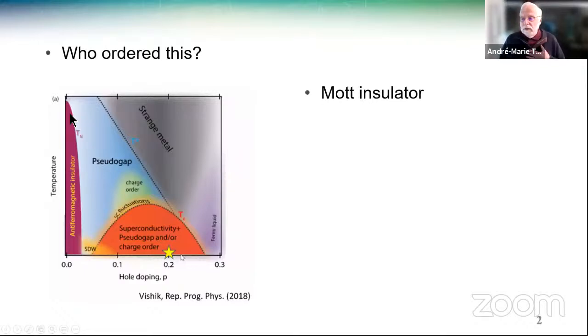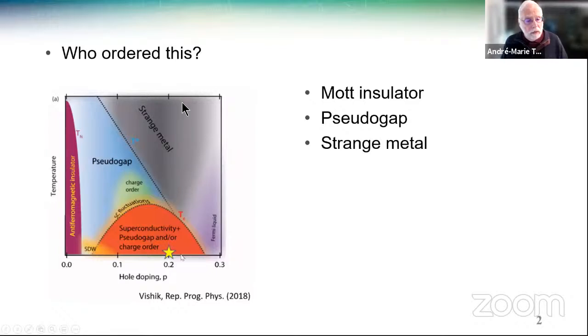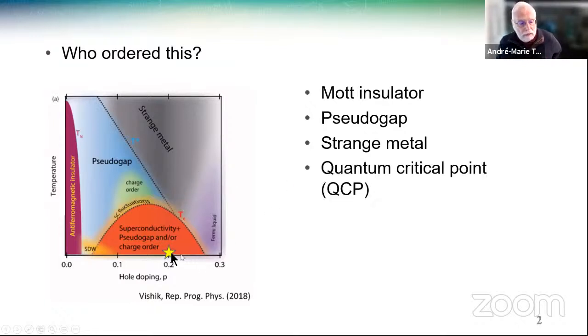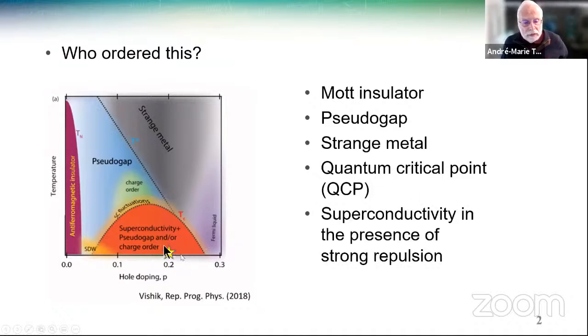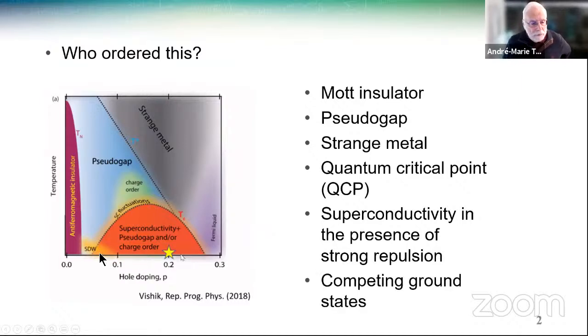In fact, you cannot use standard methods of solid state physics to understand it. For example, we know what an antiferromagnetic insulator is, but if you go above the Néel temperature, you have an insulator. Now, when you dope, so this is temperature, this is doping, you get this phase that is called a pseudogap. And here we go to a phase that has a linear resistivity, linear in temperature, that's called strange metal, and something that looks like a quantum critical point. And obviously superconductivity in the presence of very strong repulsion. This antiferromagnetism here is a sign that there is very strong repulsion. And we have competing ground states. You see a charge order here, spin-density waves, etc.